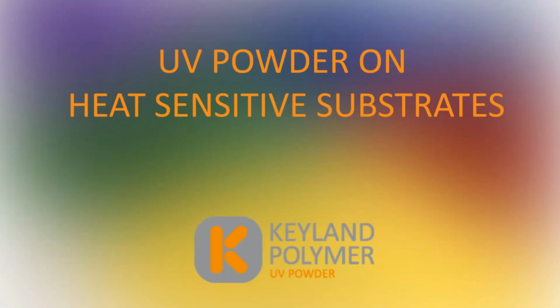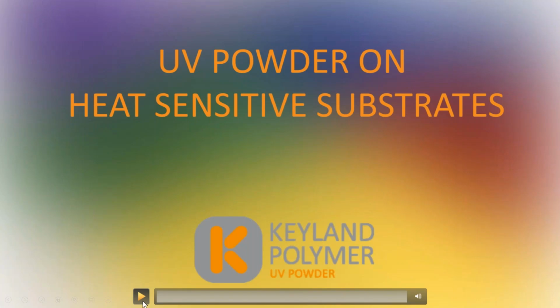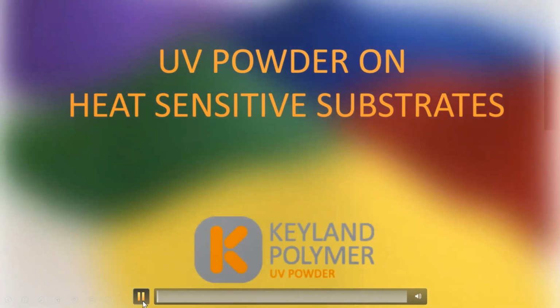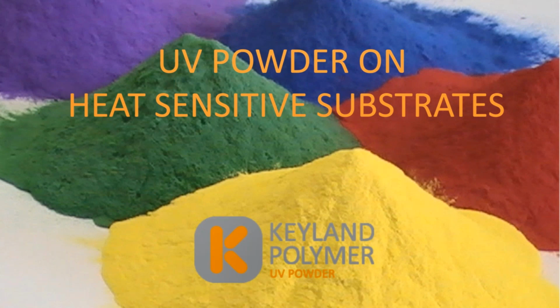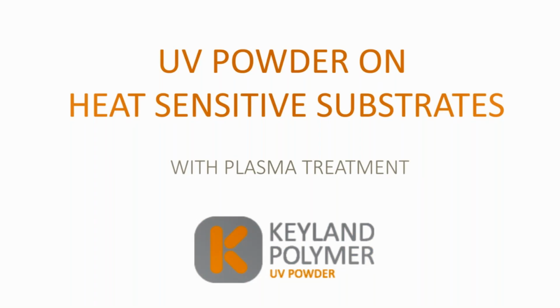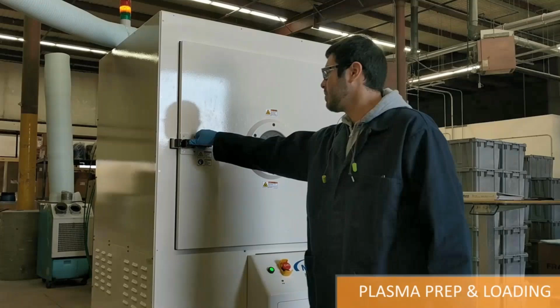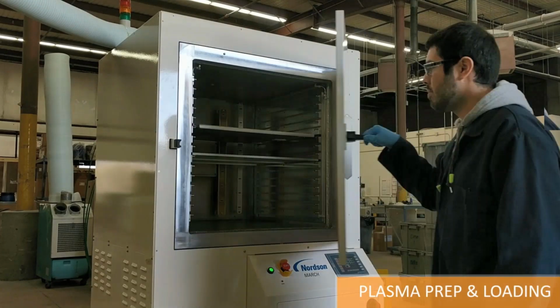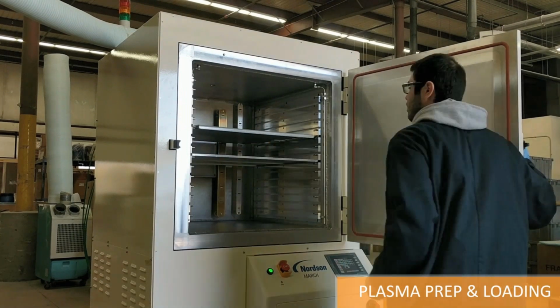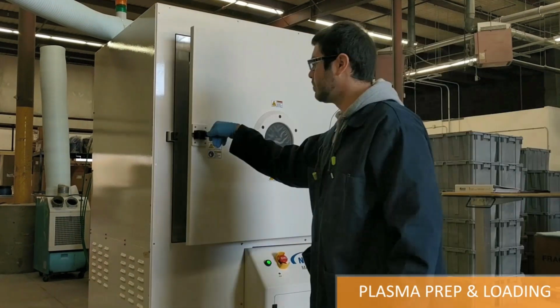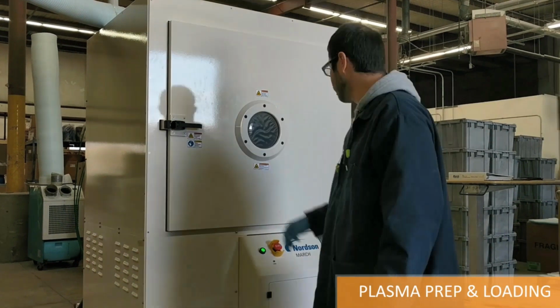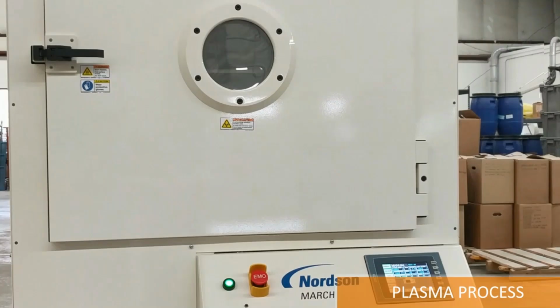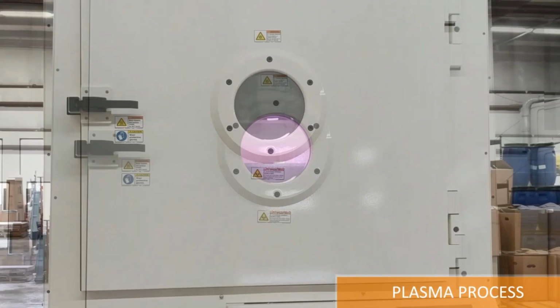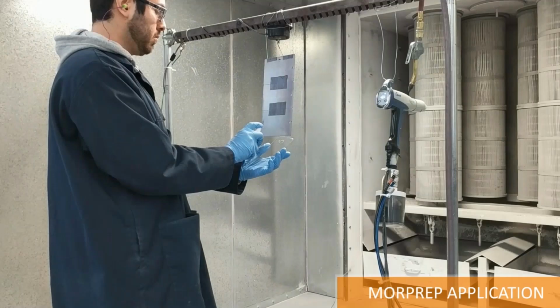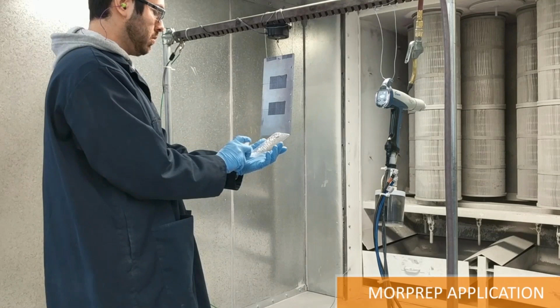So here's a video which will show all of these steps we discussed, on how we would apply a UV curable powder coating to a heat-sensitive component. So again, first we're going to take that component, put it in the plasma chamber, evacuate the air, input the process gas, create the plasma, and 3D treat the surface.